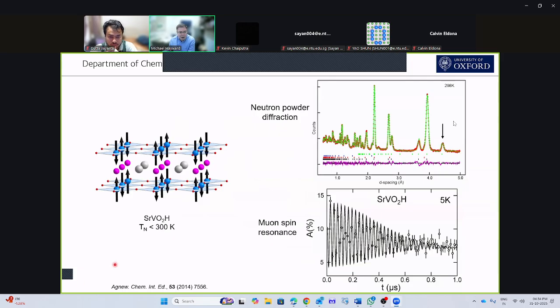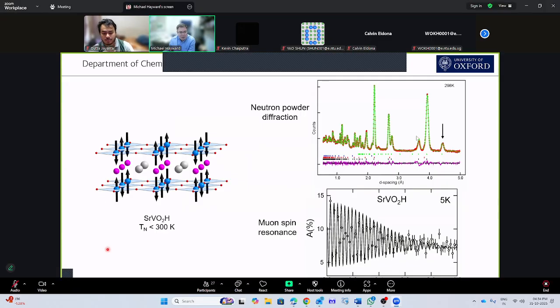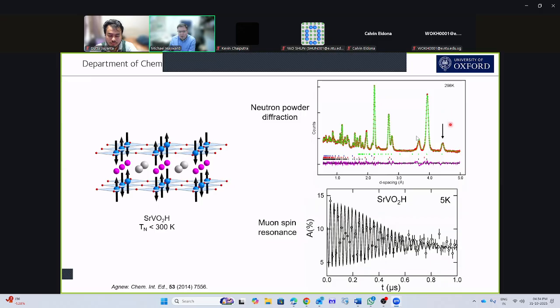SrVO2H is an oxyhydride compound based on a perovskite. What I'm showing you here is the structure where the little red dots are oxygen and the big purple ones are hydride. The material itself is an antiferromagnet at room temperature. We can see that by the neutron diffraction data here. This is a magnetic scattering peak, and from muon spin resonance, these oscillations are characteristic of magnetic order. What we see is the hydride ion is very good at coupling the magnetic moments on neighboring transition metals.